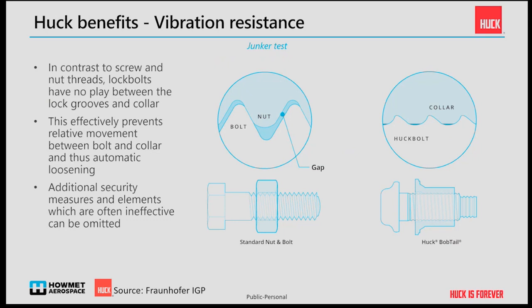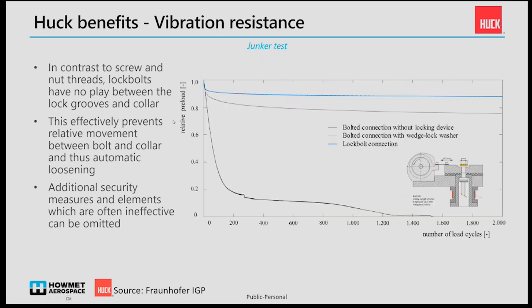So by using a swaging process, this does not occur and is proven by a so-called vibration test, the Junker test. Here we see three different curves of a Junker test. The black line is an unsecured bolted connection, and you see after only 200 load cycles, almost 80% of the preload is already gone.